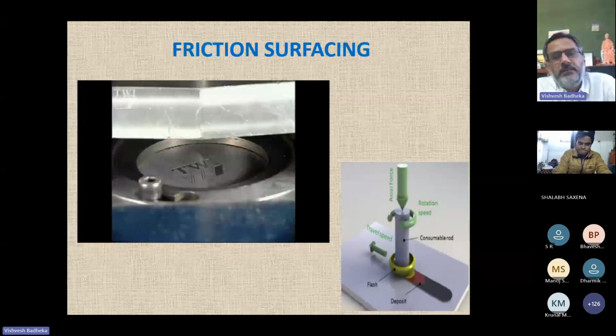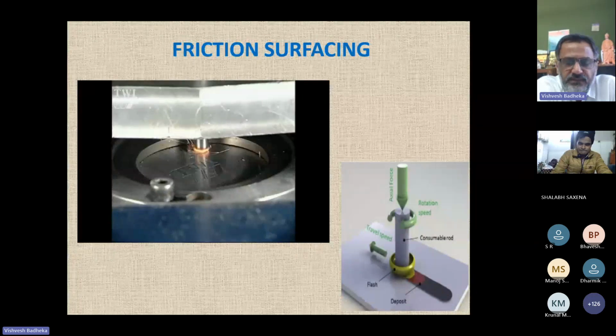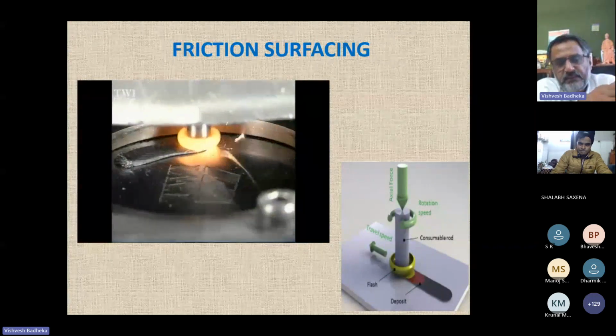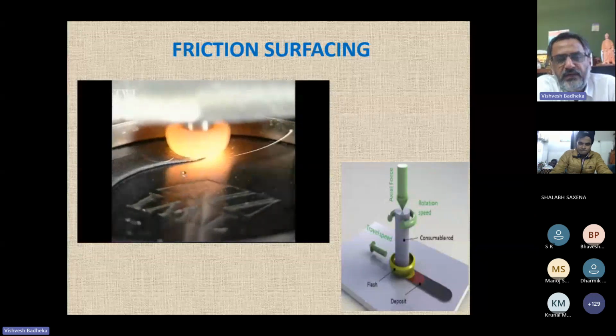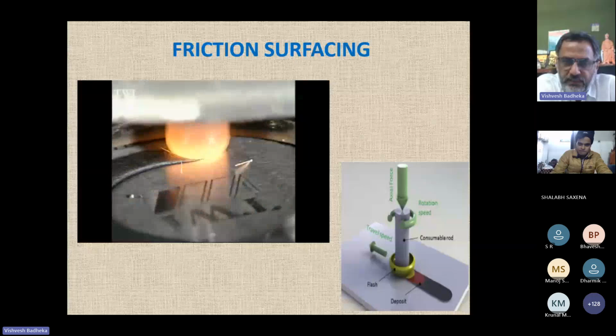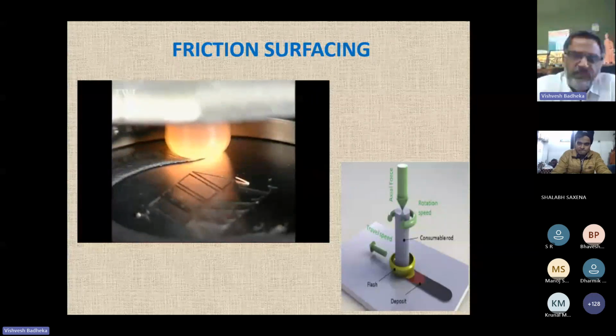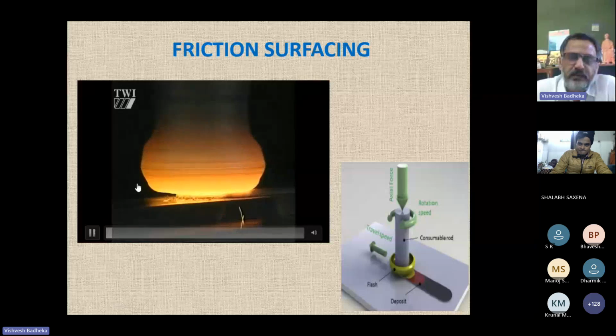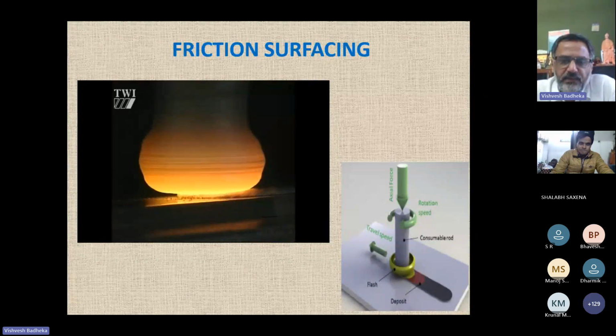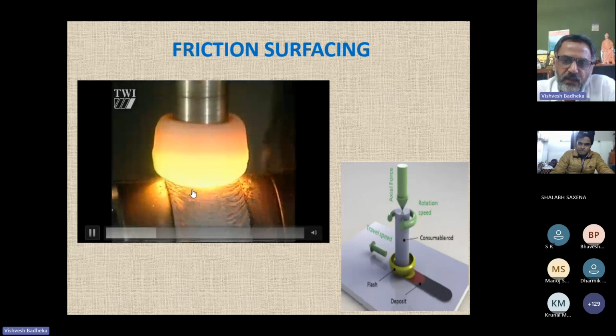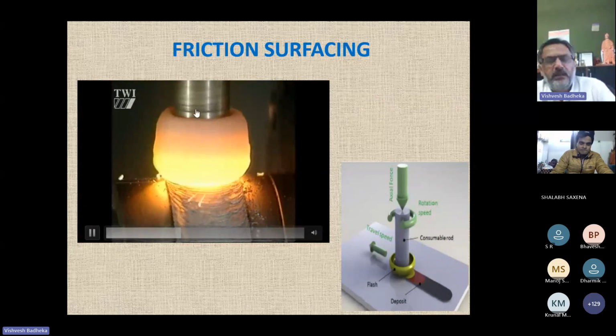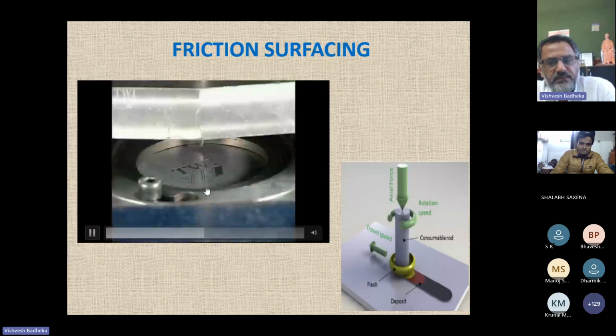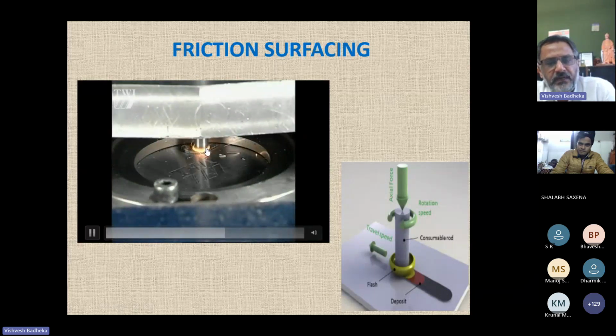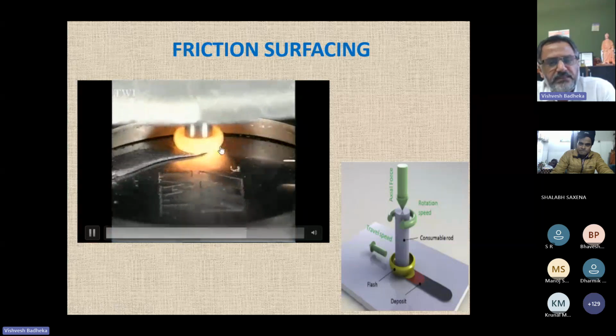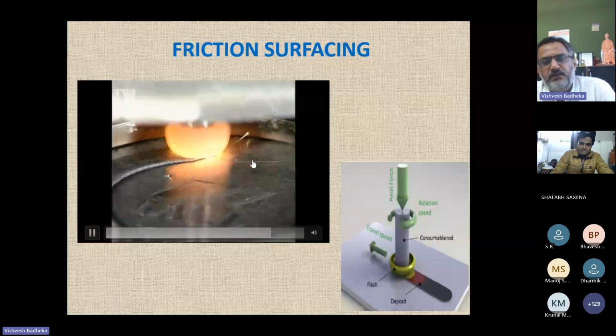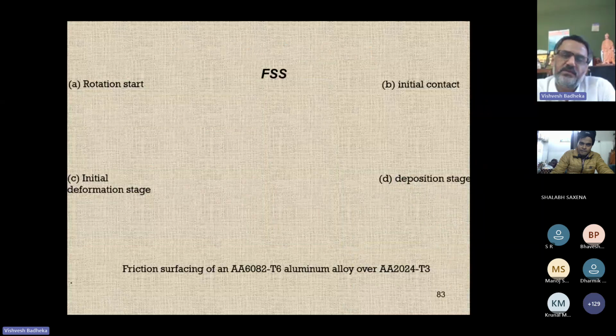So you can see here, this is the third application of friction stir processing, and it is different compared to the other two modules. Different in the sense that here you have a tool, or you can say a rod, which is consumable in nature. It gets consumed during the process, right? It is not like a non-consumable FSW tool. With friction surfacing, you are trying to clad the surface. This rod gets consumed during the process and clads onto the surface. Initially it is like a tapered pin, and then you can see the deformation starts immediately and it is getting clad onto the surface. This process is called friction surfacing.